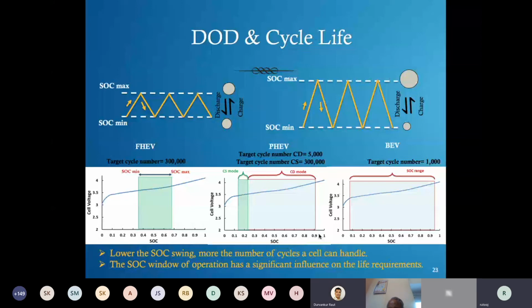Yeah, so we have some LFP cells lying at our office from the last 3 years, and nobody had touched them. When we took them out of the stock, they were still performing well. Not up to the mark, not to the full capacity, but they were still performing. So there are two things, right? One is degradation that is happening continuously, and there is self-discharge. Self-discharge is kind of recoverable capacity, in addition to the degradation. The voltage was also around 3.2 V for them, which is typically seen in these LFP cells.